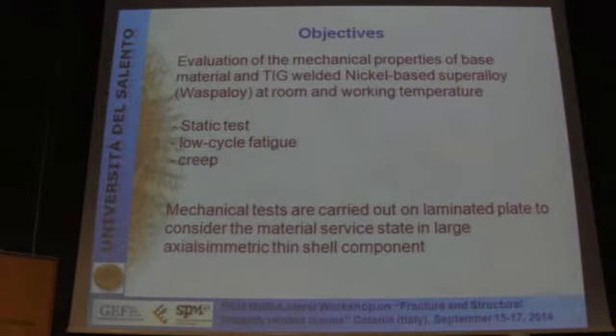In this work, we considered TIG welding as a repair technique, and we considered the case of a nickel-based superalloy, Waspaloy, which is very diffuse in the aeronautical field. To do this, we performed static, low-cycle fatigue and creep tests on the base material and on the TIG welded material.